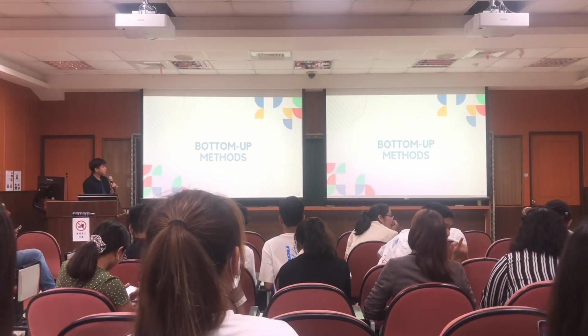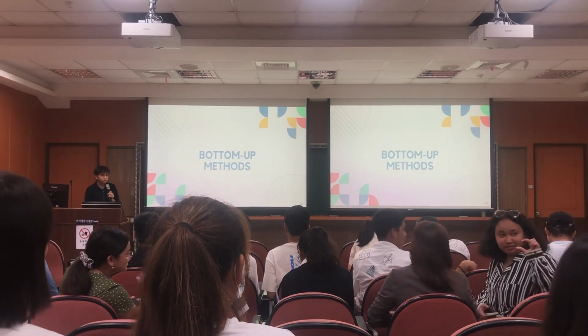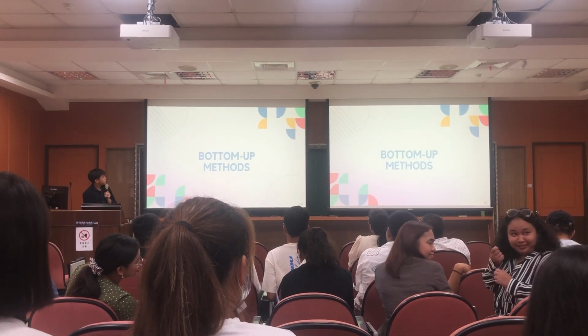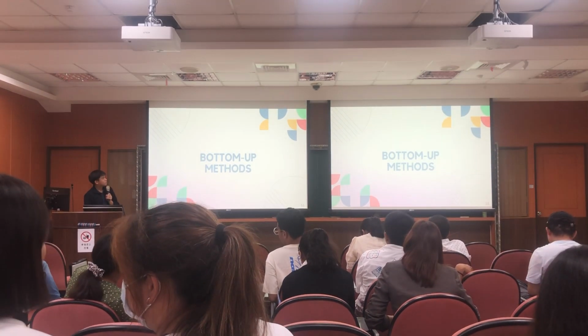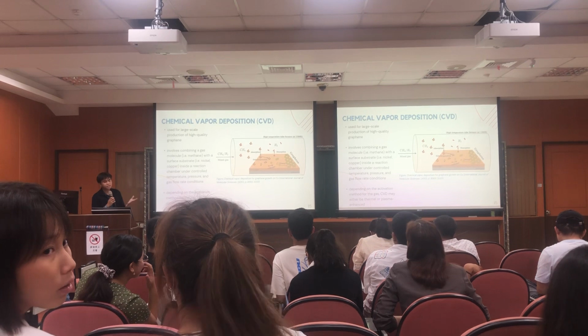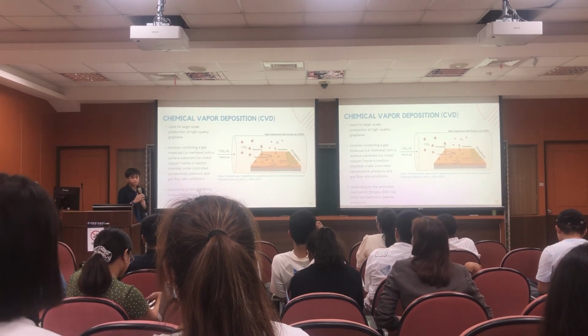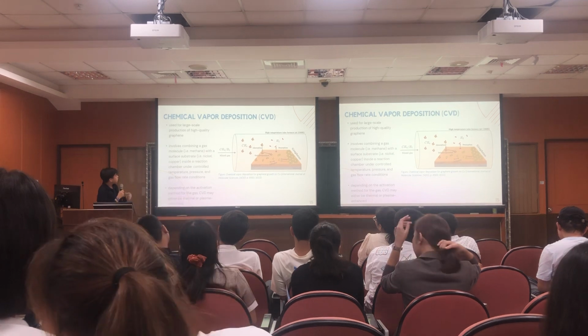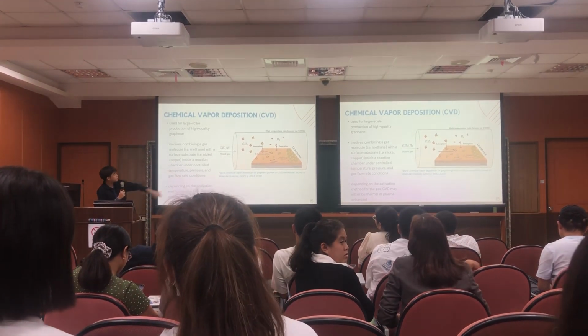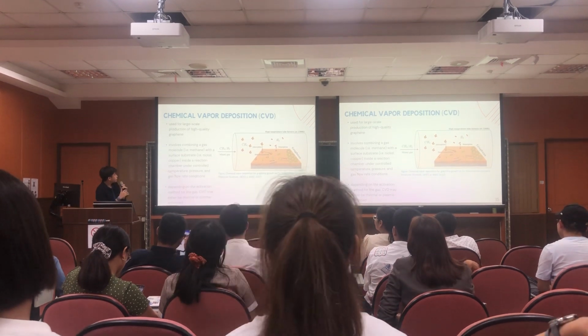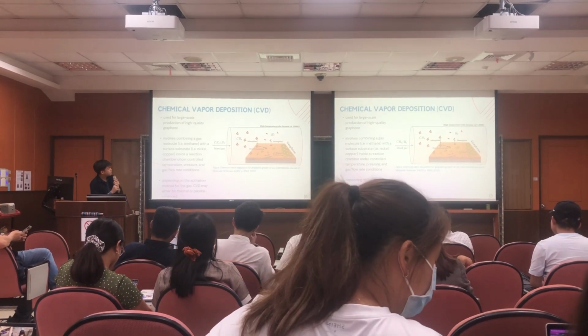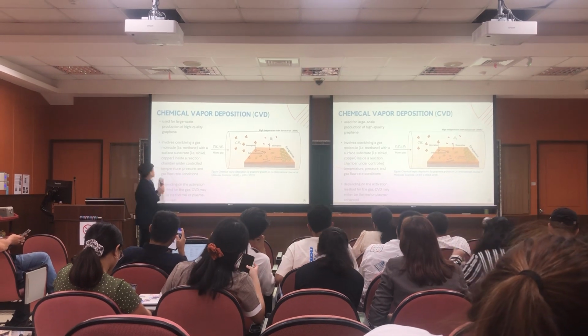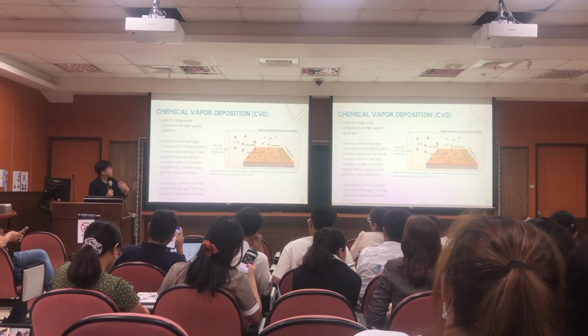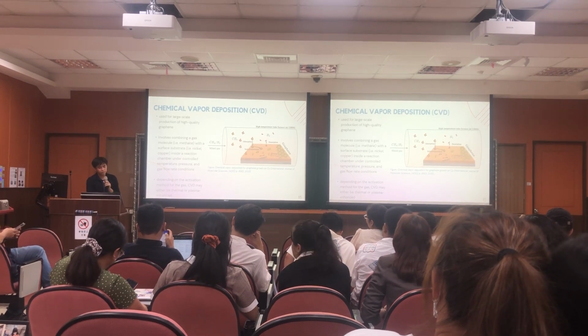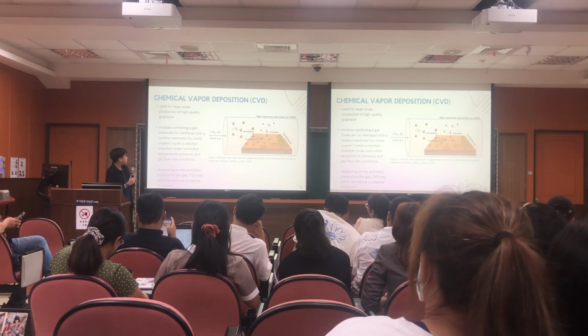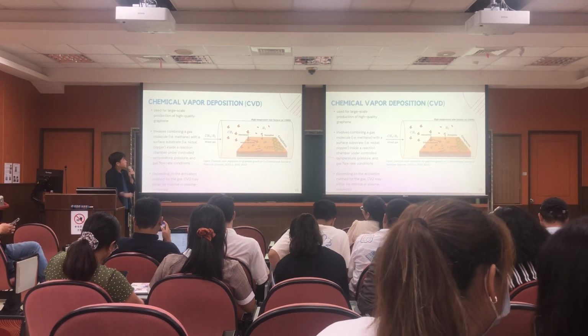Next, it's a bit heavy, so let's go down to our bottom-up methods. There are two major bottom-up methods which researchers find highly applicable in their studies. The first is chemical vapor deposition. It is used for large-scale production of high-quality graphene. It involves combining gas molecules, and as seen in the figure, methane and hydrogen, while using a surface substrate. So there's your copper on top as a catalyst. And the machine that you perform chemical vapor deposition with is able to control your temperature, pressure, and the flow rate of the gases moving into the chamber.